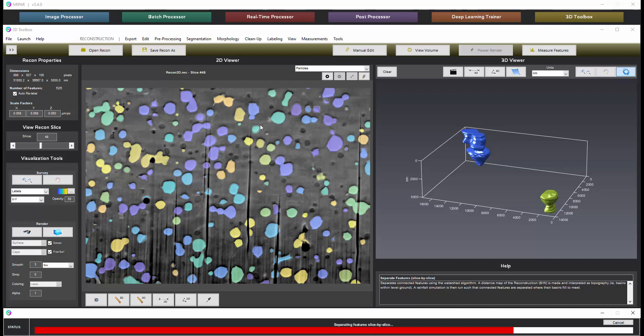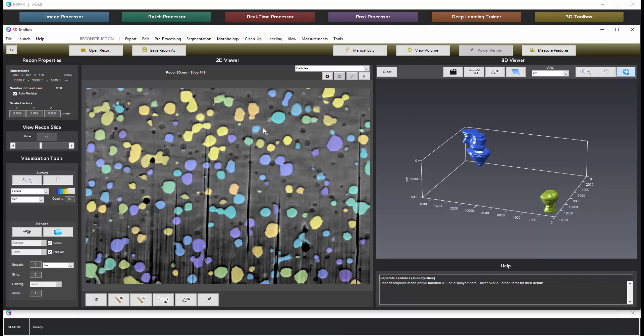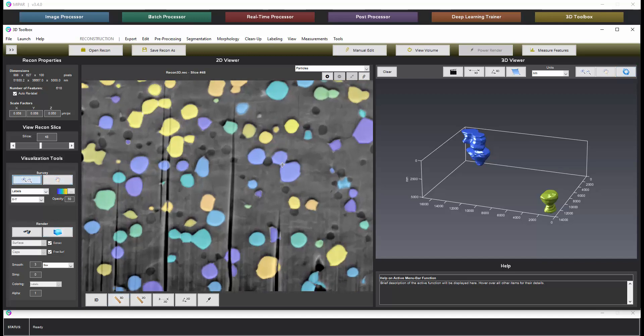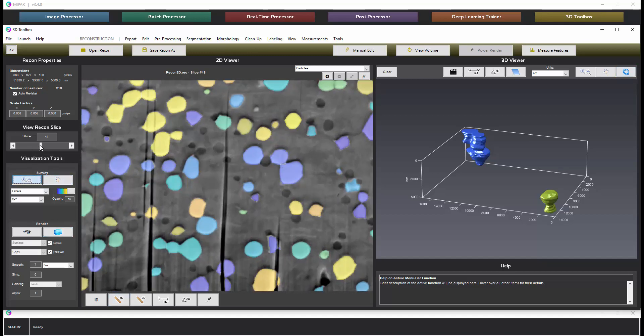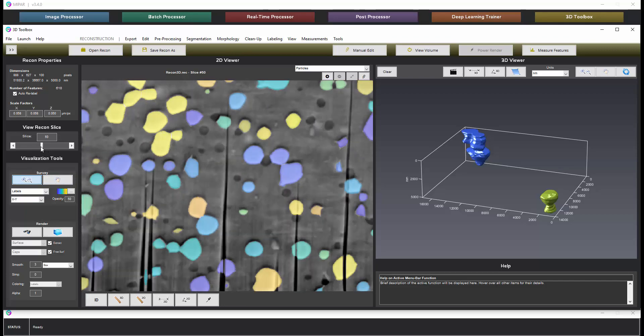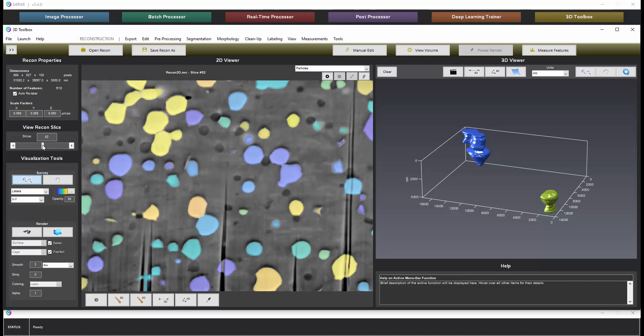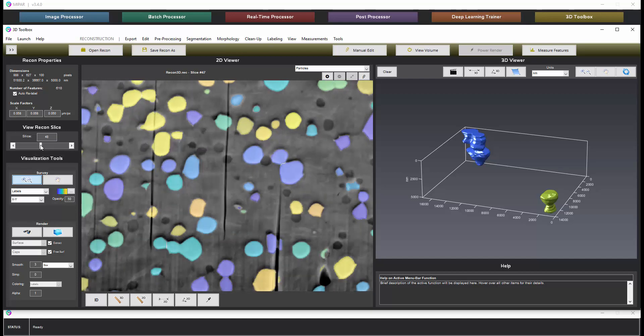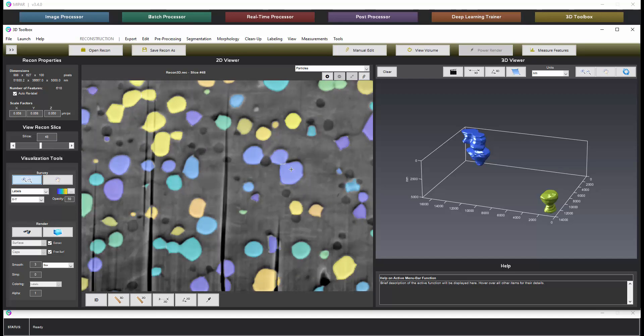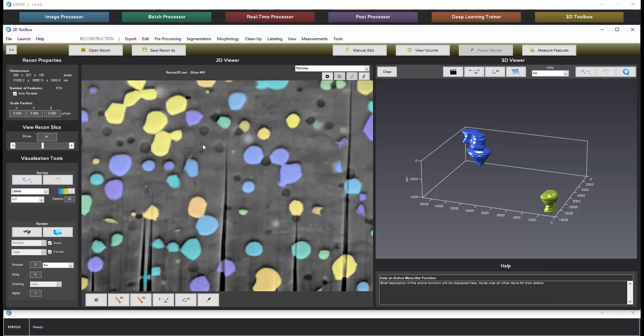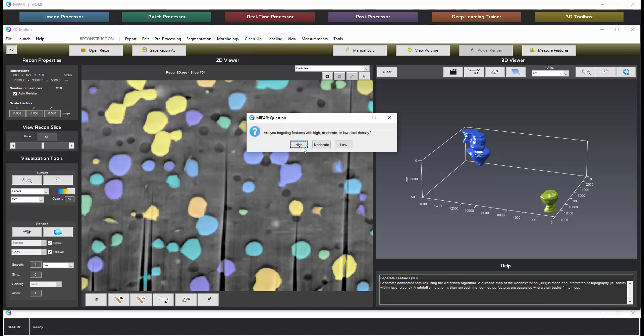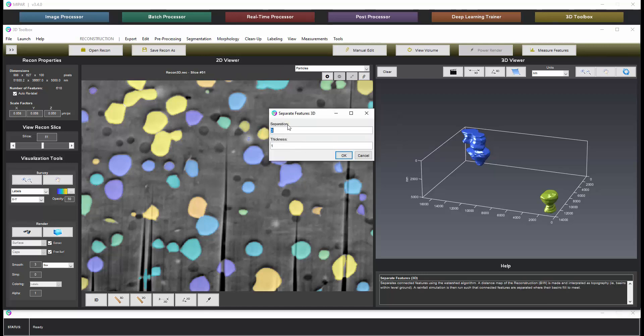We'll see that the separation likely won't be complete so we can then reapply in three dimensions. So you see while there are some cross sections of a feature like this that have been separated that may have not been made fully in three dimensions there might be a pixel or two still overlap in the Z dimension that causes the software to still view this as one feature. So to complete it we'll run it again but in three-dimensional mode. So we'll go to separate features 3D. Generally you'll choose high and we'll enter the same separation of three that we did in 2D.